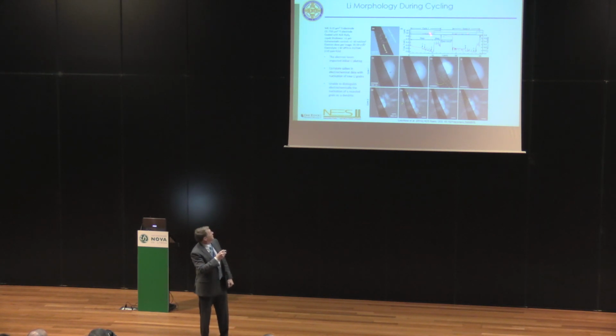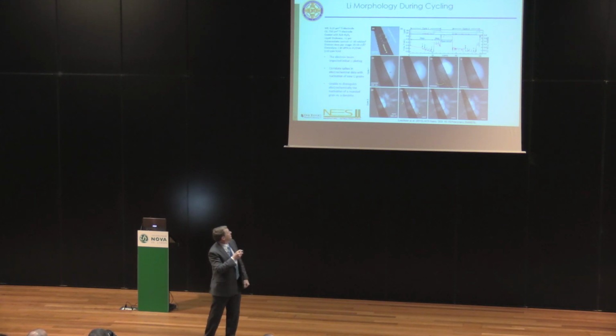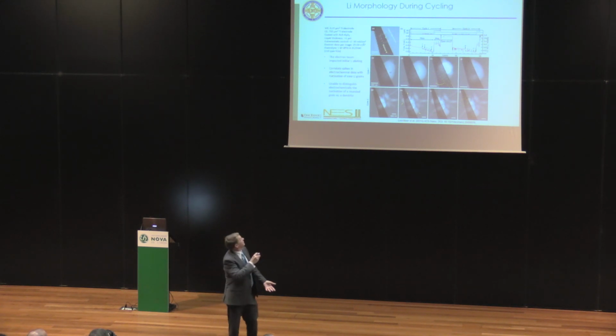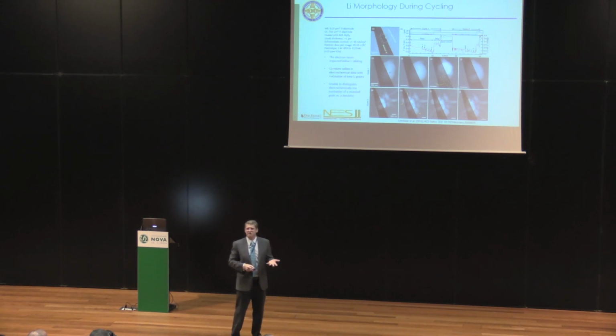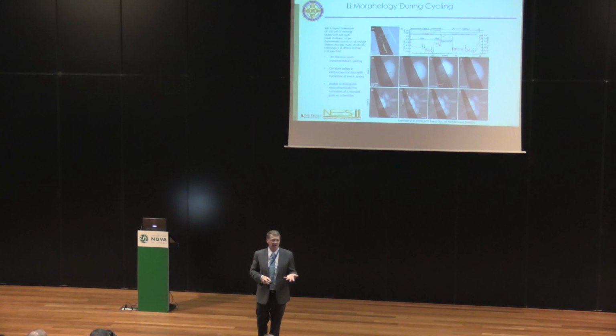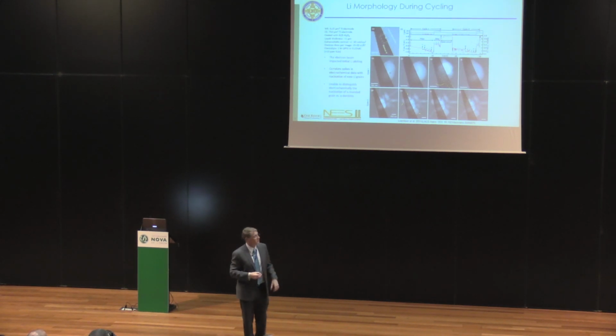Over here is the trace of the current versus time. You see initially there's negative current, so they're plating out the lithium, and you can see the current is actually held constant. So this is a galvanostatic deposition of the lithium, or charging it. You're holding the constant current while depositing the lithium. This is the common mechanism that you'll see in the community when you're actually doing charges of batteries.